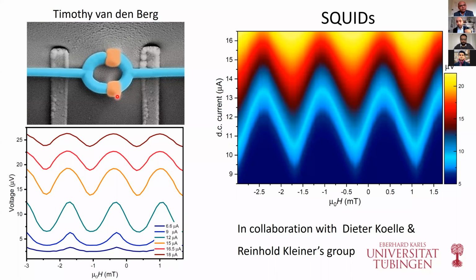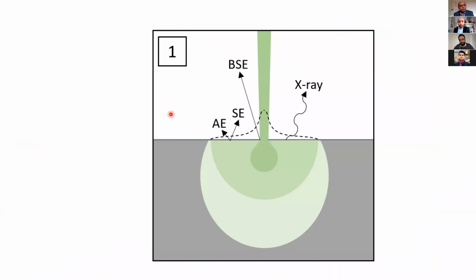And that's because they're using a much lower beam current. Here we're using a much higher beam current, which means that you have a bigger spot size on your surface. And that's one thing. And secondly, as I said, the EBID process is a little bit more complicated than what I showed you, because here is the incident beam. In our case, this incident beam is only about 40 nanometers in diameter. But why does this wire look so much wider? That's because of the secondary electrons, which are also contributing to the dissociation of the molecules.